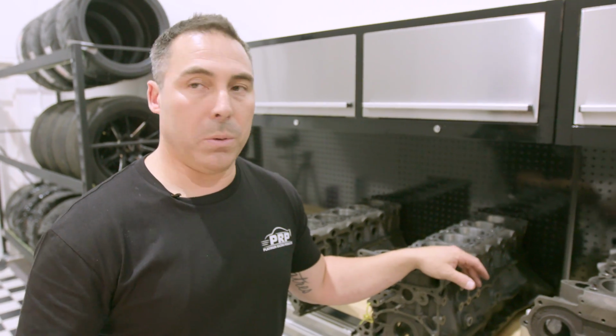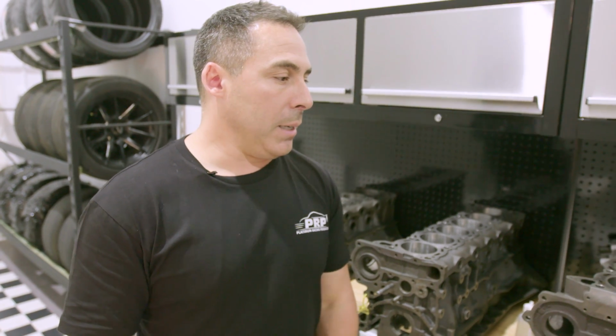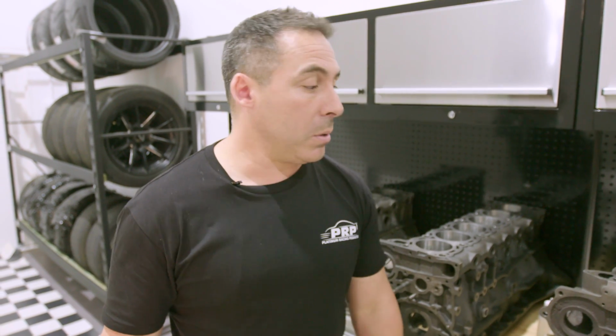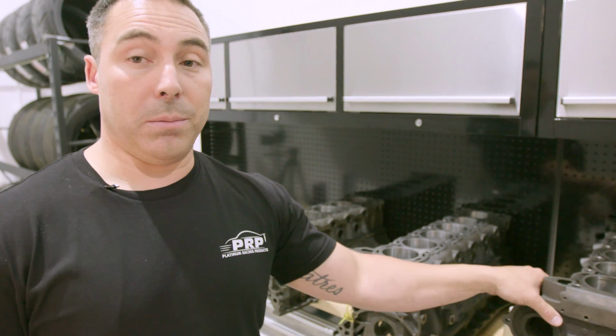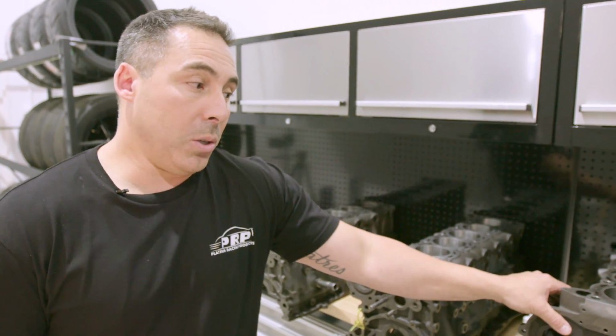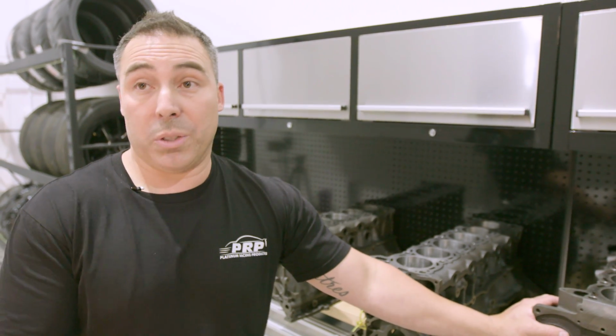They are always random across the board. You can't leave a particular part of the bore untouched because you never know what you're going to get. So you really do need to spend the time in each bore to work out where the thinnest part is, and then you can start to build a report. So far, this one goes to show we're getting pretty thin on the front face of cylinder 2 there. It's up the top where it's getting thin, just over 3 mil. An offset bore will save that block.